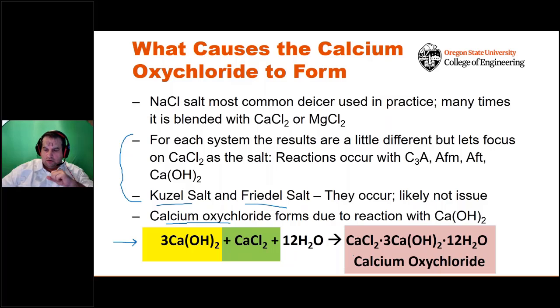So first, it's scary because it's a great big long equation. The second reason it's scary is it's the calcium hydroxide that combines with calcium chloride and water to form this calcium oxychloride. And you may say, well, we don't have any calcium hydroxide in our system. Yes, we do. Because when cement reacts with water, two things are produced. We produce calcium silicate hydrate. That's the good glue for anybody who's a big Wizard of Oz fan. That's the good witch, all right? And we have calcium hydroxide, the bad witch in the system.